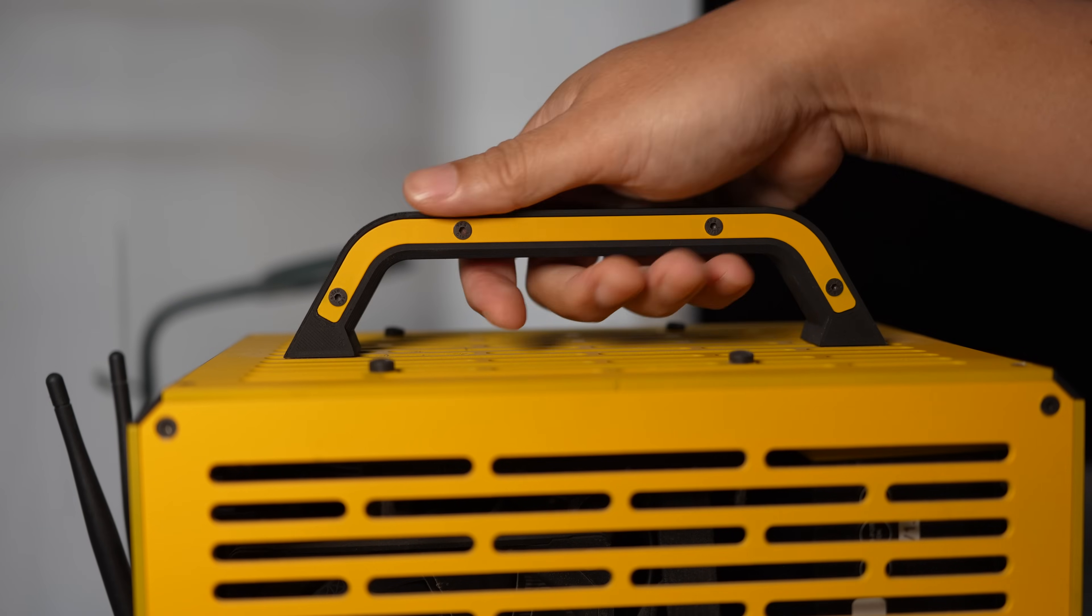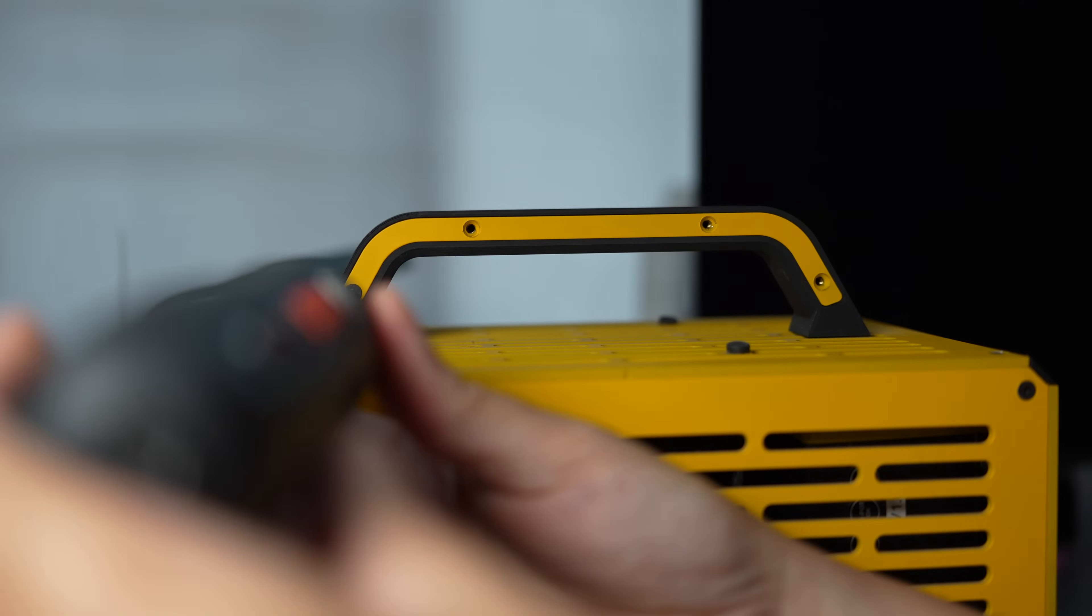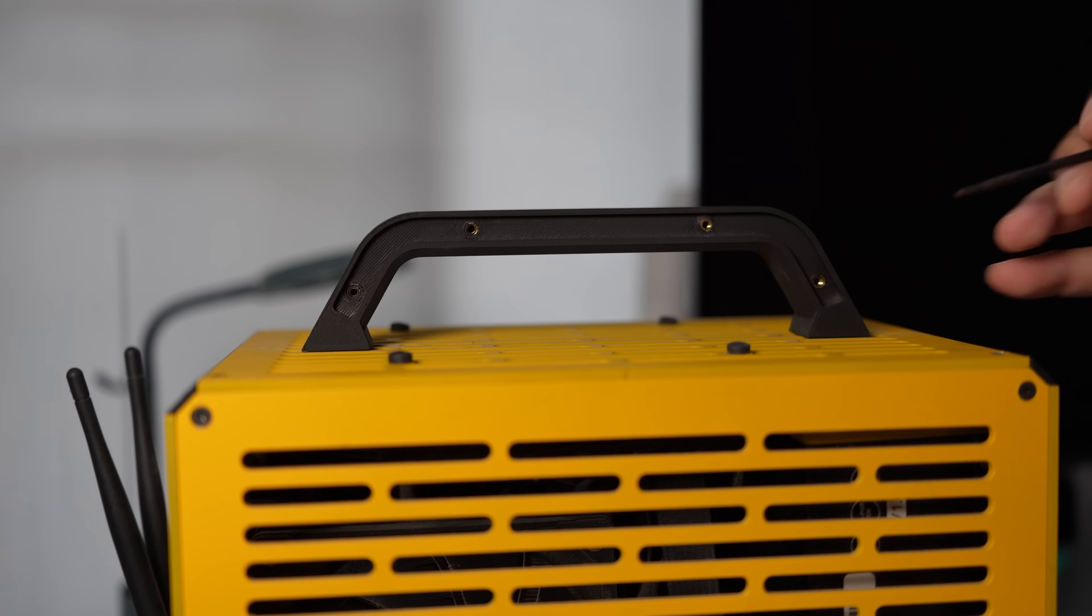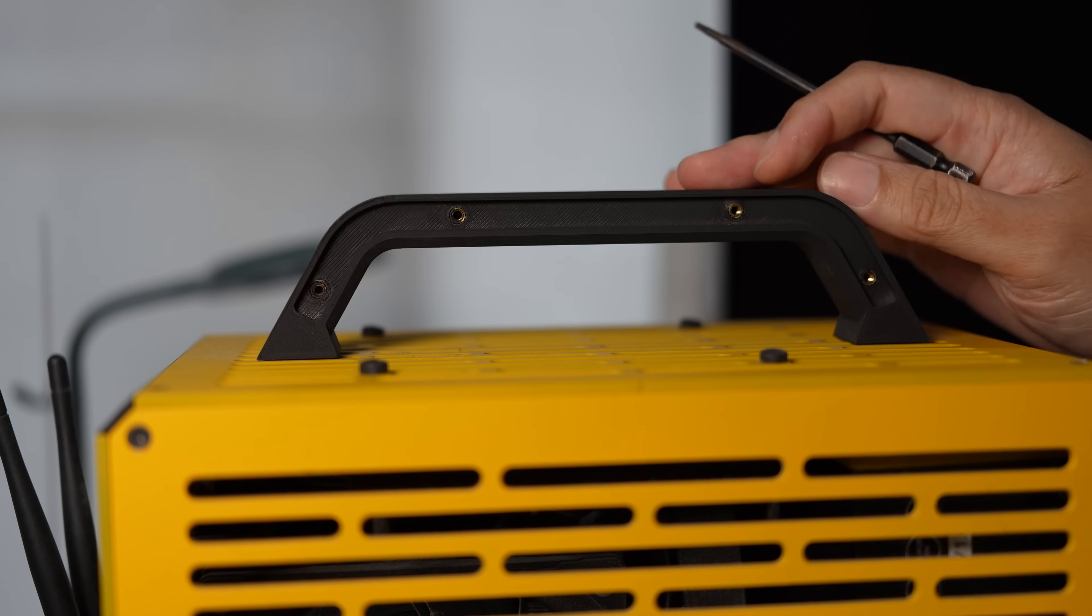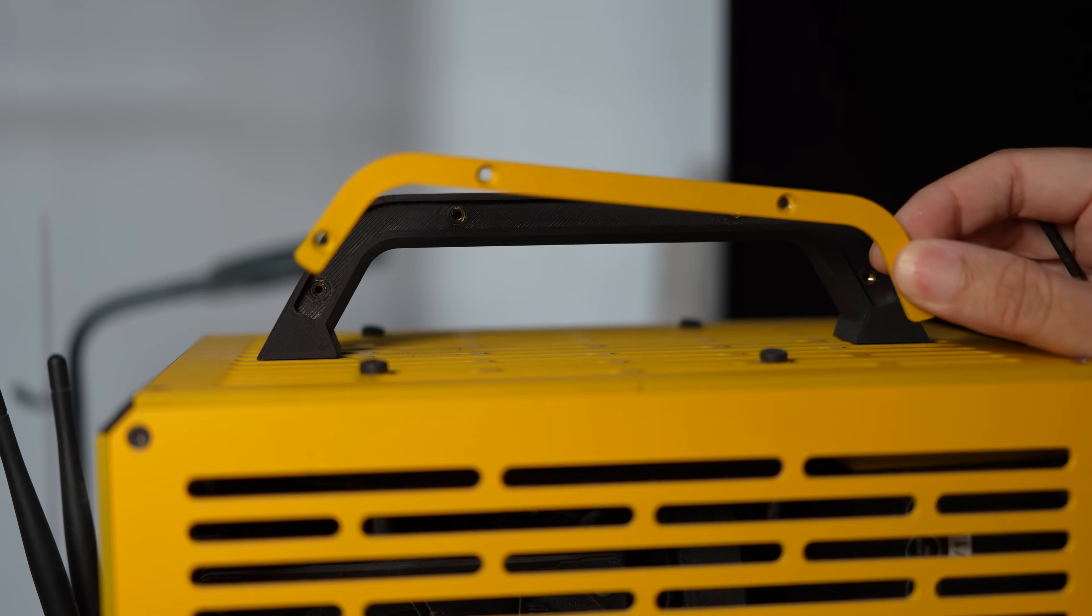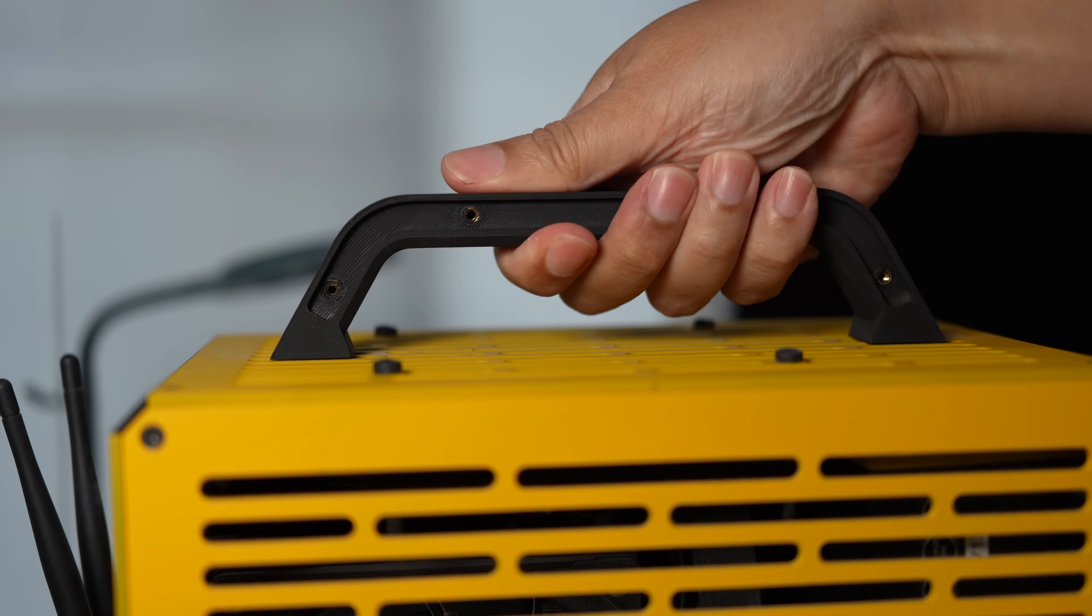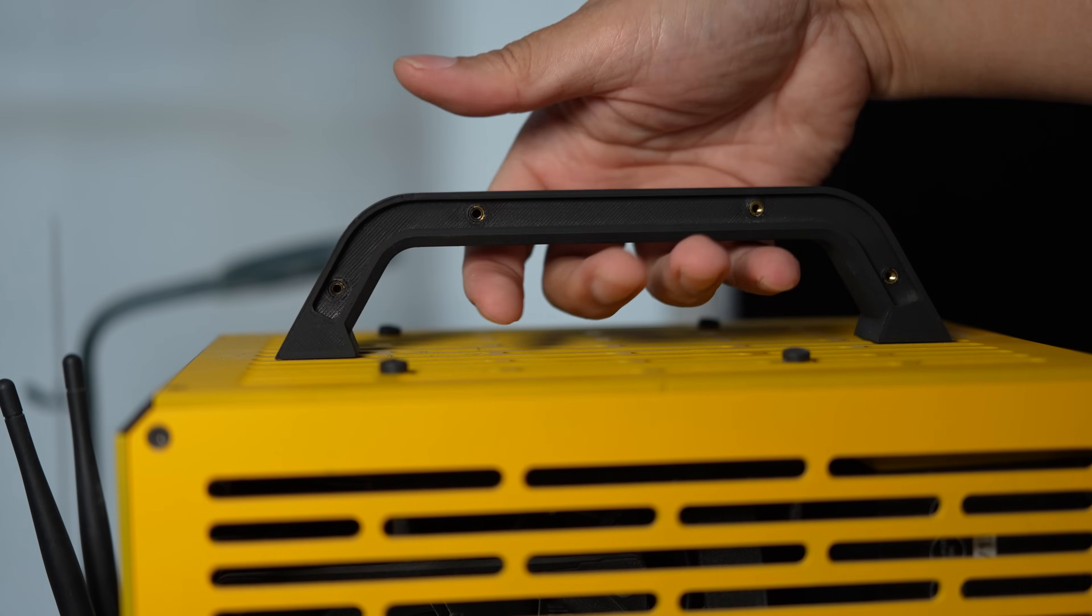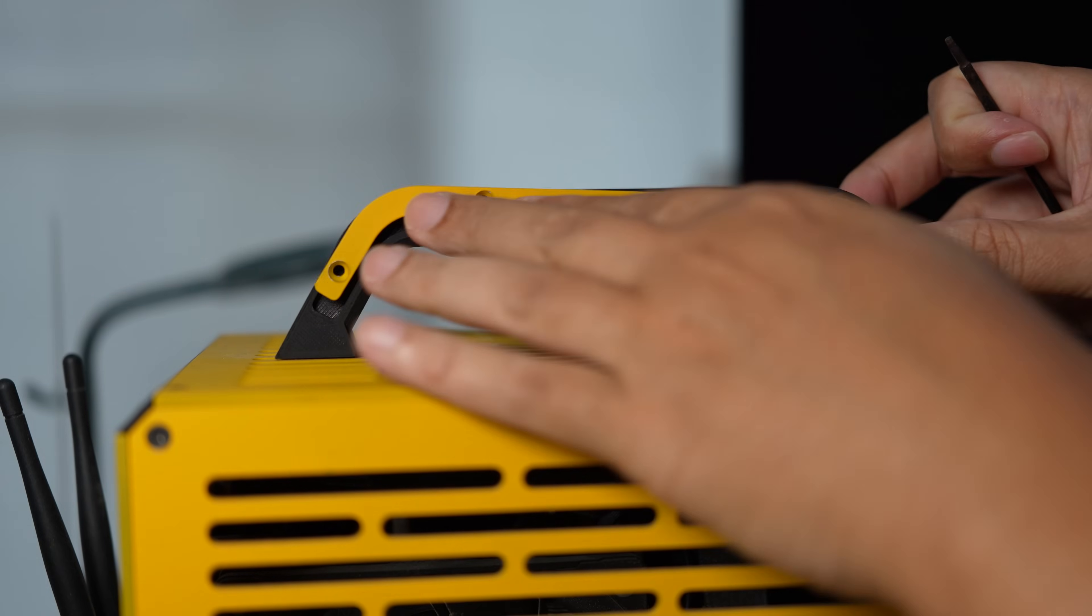Okay, this is a handle of a computer case. What I do is I create a pocket. I use M3 brass insert, place it into the 3D printed parts. And this one is 3 millimeters aluminum plate, I cut with the CNC machine. It doesn't cost that much because it's quite easy to make. Without the aluminum, this handle will flex and when you hold it, it will feel insecure. So if I put the aluminum plate in there, the aluminum is stiffer than the ABS.